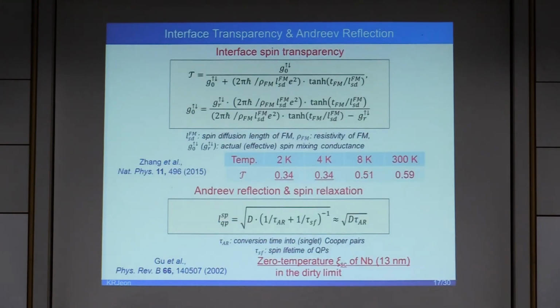The role of the superconducting state in the spin injection and spin transport can be understood in terms of interface spin transparency and diffusive penetration of spin-polarized quasiparticles, which is progressively suppressed with the decrease in the temperature. The transmission of non-equilibrium spin accumulation generated on the ferromagnetic side to the non-magnetic layer depends on the matching of electronic band structure in two different materials on either side of the interface, which can be quantified as follows. We can then see that the spin transparency for the permalloy niobium interface is much lower when the niobium layer is superconducting, supporting that the reduced spin injection efficiency is ascribed to the band structure mismatch due to the presence of the superconducting energy gap.